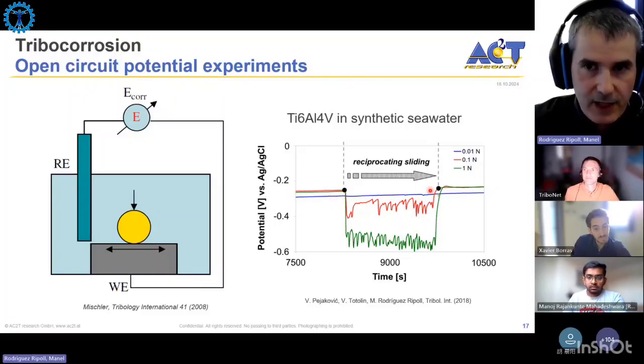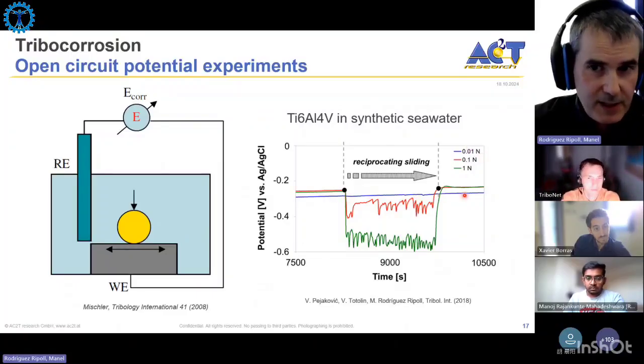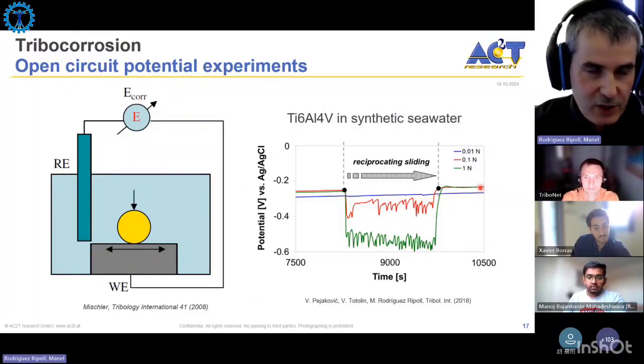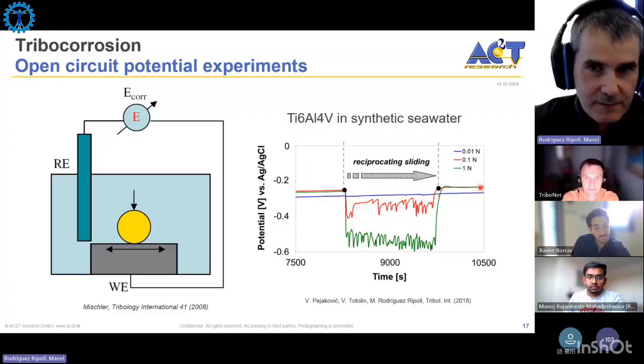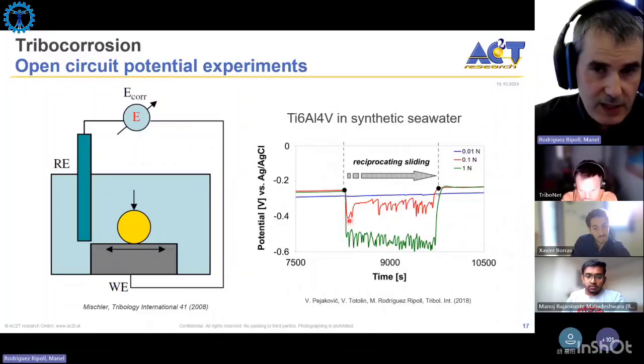If we have a very little load of 10 millinewtons, when we start the sliding, basically nothing happens. It means that we don't have any change in the passive layer or in the surface composition of our material. If we apply a higher load of 100 millinewtons, then we see a shift of the open circuit potential towards cathodic values. We see that this is not stable, so the potential sometimes goes back to higher values.